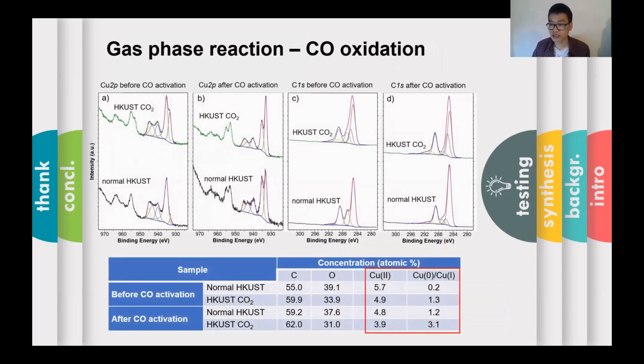First, we test this sample in a gas phase reaction. Here we use the CO oxidation reaction as an example, because the copper site in HKUST-1, the MOF that I'm working on, has shown some activity in this reaction. Before the reaction, both samples were activated in a flow of CO to remove the coordinated molecules on the copper site in the MOF.